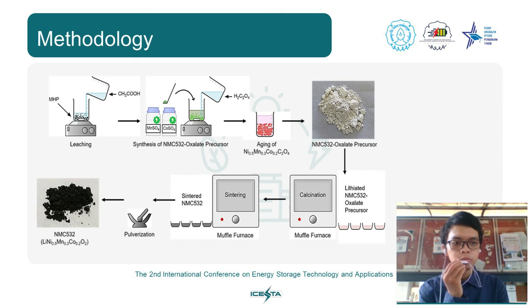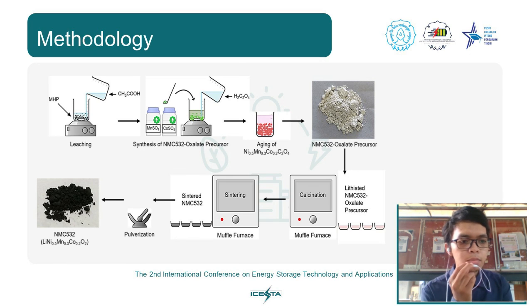Here is the methodology to produce NMC 5:3:2 cathode material. The first step is the leaching process. After the leaching process, we add manganese sulfate, cobalt sulfate, and oxalic acid to get NMC 5:3:2 oxalate precursor. And then we let it age overnight to get the precursor. After that, we calcinate the precursor by adding lithium carbonate in excess 10%, and then we sinter the material to get NMC 5:3:2, and then we